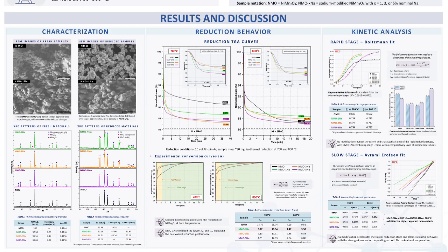The conversion curve showed two distinguishable regions, an initial rapid stage followed by a slower stage. The rapid stage was described using a Boltzmann function. The parameter L represents the contribution of this stage, while tau represents its characteristic transition time. Sodium affected both parameters, with the 1% sodium sample showing a favorable combination of a large rapid stage contribution and a short transition time.